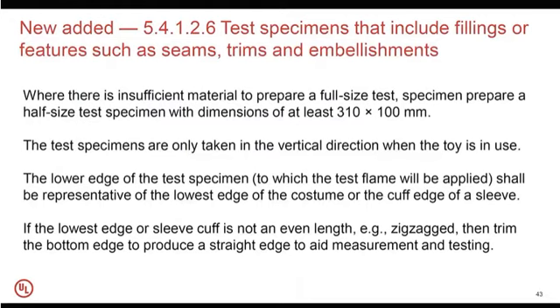But if there is insufficient material to prepare a full-size test specimen, you can prepare a half-size test specimen with a dimension of at least 310 per 100 millimeter. The test specimens are only taken in the vertical direction when the toy is in use, and the lower edge of the test specimen to which the test flame will be applied shall be representative of the lowest edge of the costume or the cuff edge of a sleeve. If the lowest edge or sleeve cuff is not an even length, for example zigzagged, then trim the bottom edge to produce a straight edge to aid measurement and testing.